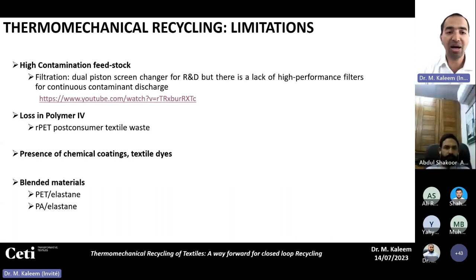Yeah, so if your feedstock contains high contamination, you may have a big challenge during processing, so you may require high filtration. In the market, there are a lot of different types of filters available. This is the continuous filter that I gave as an example for industrial scale filtration systems. And then we have a second challenge during textile recycling. We lose the polymer IV. Polymer IV is related to the polymer molecular weight. So after recycling, the polymer IV decreases, and then these pellets may not be suitable to develop fiber out of that.